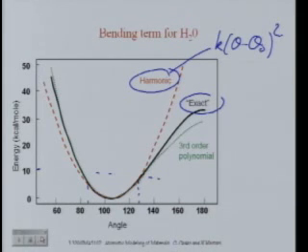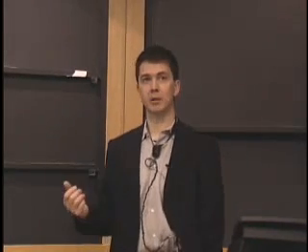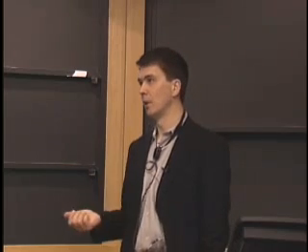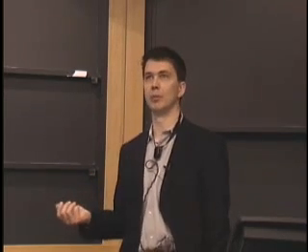Notice that a quadratic, by its nature, is always too weak on one side and too stiff on the other side, because the real potential may be asymmetric. But with a third order polynomial, which is the green line here, you're already doing very good. So you often don't need really complicated functions of these bond angles, because usually the more complicated your functions, the more can go wrong when you fit as well.